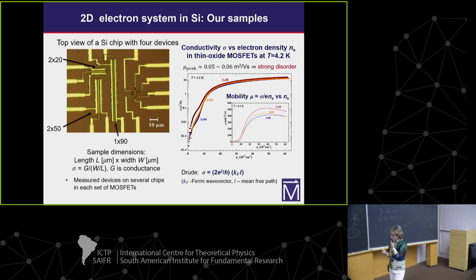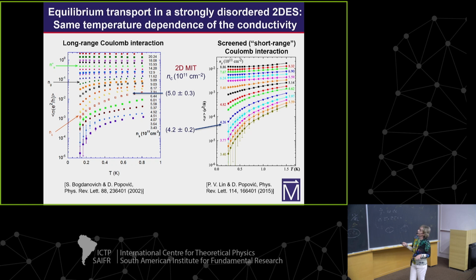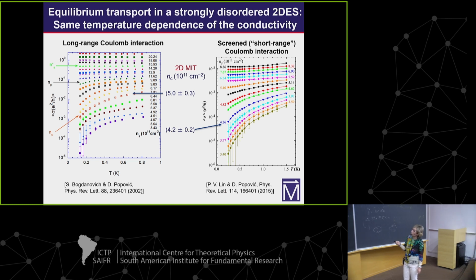First we want to compare the equilibrium behavior of these samples. This is something we did quite a long time ago in both sets of MOSFETs. In each graph we have conductivity as a function of temperature for different carrier densities, from high to low. What we see in both cases is that the temperature dependence at high densities is weak.